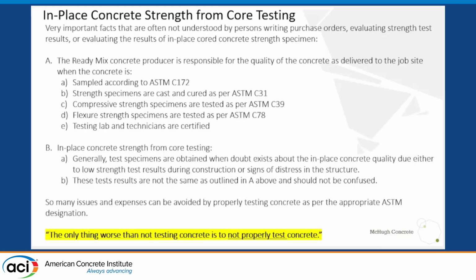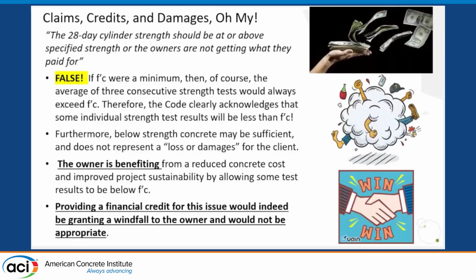The in-place concrete strength from core testing, generally test specimens are obtained when there's doubt about the in-place concrete, either due to low strength tests or possibly signs of distress. And these test results are not the same as outlined in A, and they should not be confused. So the stringent control of the sampling and the testing is not as rigorous as it is in A. And claims, credits, and damages, oh my.